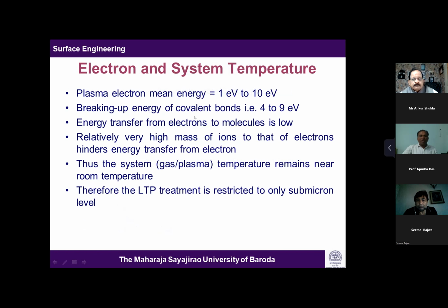I was telling you about the plasma system temperature. Sometimes we have to correlate that the electron energy ranges around 1 to 10 electron volts, and the bond-breaking energy of a covalent bond is in the range of 4 to 9 electron volts. Therefore, we have to consider what kind of covalent bond we are dealing with and what energy range we have to keep in the plasma. We have to map this so that we can initiate the required chain reactions and chemical reactions.